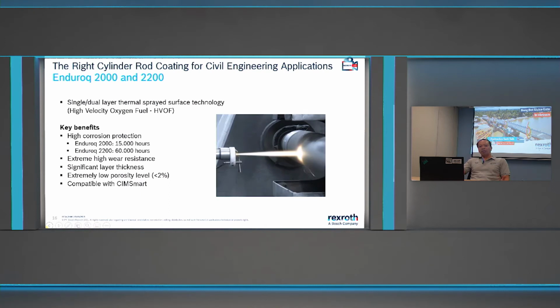So the benefit of this coating is very high corrosion protection. Like for Enduroq 2000, they can withstand 15,000 hours, and for Enduroq 2200, which means the dual layer, you can have 60,000 hours with the salt droplet test. This coating has extremely high wear resistance, significant layer thickness, and extremely low porosity levels. And this coating is compatible with CimSmart.